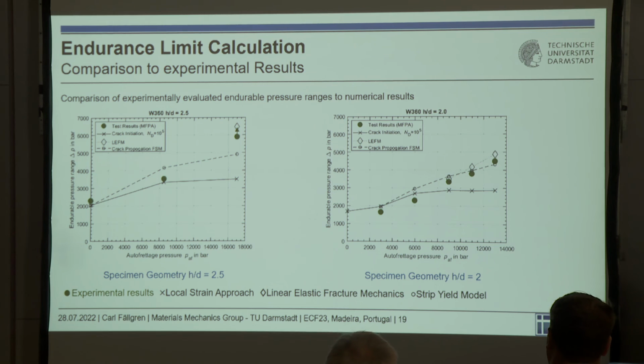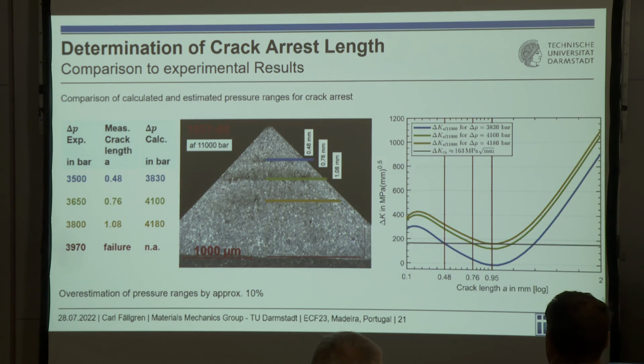But what I'm going to go into right now is, can we really see the difference between crack initiation and crack arrest? So you see this little mark I made around the specimen autofrettaged at 11,000 bar on the right-hand side. And as I told you, these specimens, which are the thinner ones, were tested with the pressure raising technique. So we applied a load. If it survived 10 to the power of 6 cycles, then we increased the load and so on. And then we broke open this specimen.